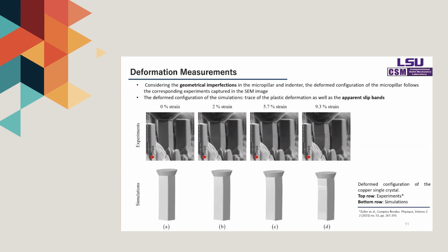Considering the geometrical imperfections in the micropillar sample, the deformed configuration of the simulations are well matched with the corresponding experiments in terms of the trace of plastic deformation and apparent slip bands. So you see here the slip bands from the simulation, which are mimicking the experimental values that you can see here.